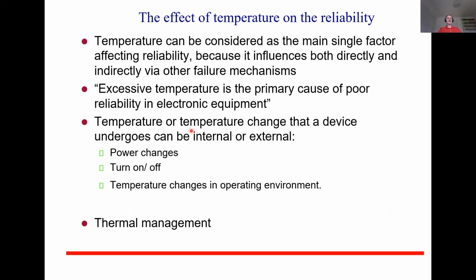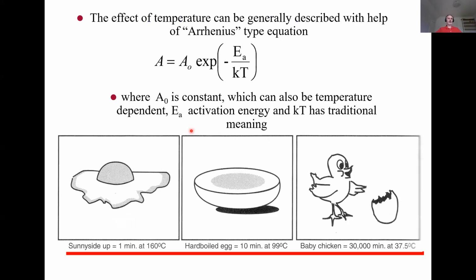And as temperature is the most important factor, then of course, as was shown already in the first or second lecture, the lifetime estimation equations or prediction equations practically always contain this Arrhenius part. So again here, this is the Arrhenius equation. Anything which is happening in nature is somehow exponentially dependent on temperature, and this activation energy term here describes how large the effect of temperature is.